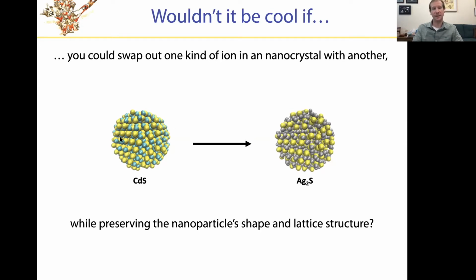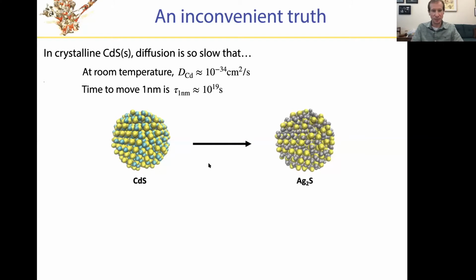This all has to happen in the context of a highly ordered and relatively stiff solid material. As you might imagine, very dense materials that are also very stiff and highly ordered don't encourage motion of atoms or molecules or ions over substantial scales. You can make measurements and extrapolations that tell you in a material like cadmium sulfide just how rapidly atoms or ions tend to move through the crystalline lattice. And what you find is that at room temperature, that motion is characterized by a diffusion coefficient that is this very, very small number, but it's in macroscopic units. So if you don't play around with diffusion coefficients all the time, you might not know exactly what that's telling us. So let's put that in more concrete terms.